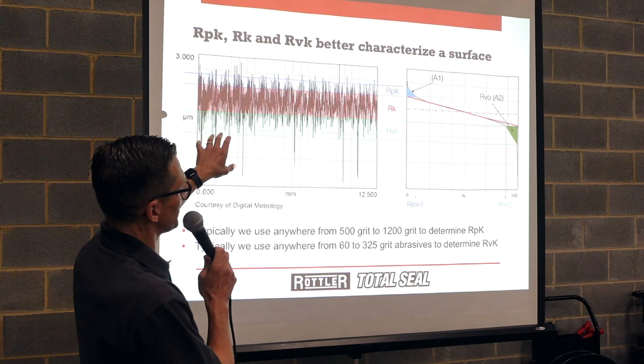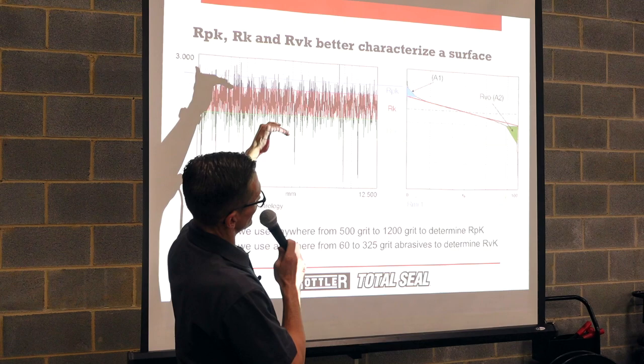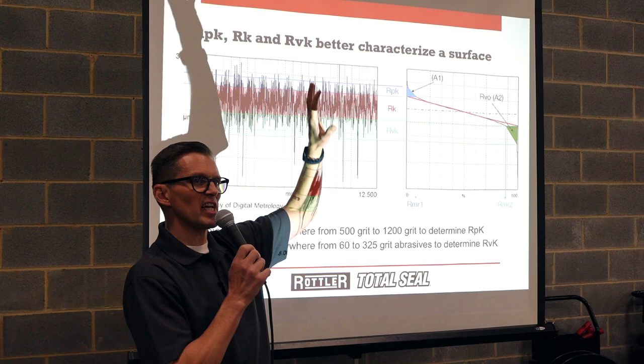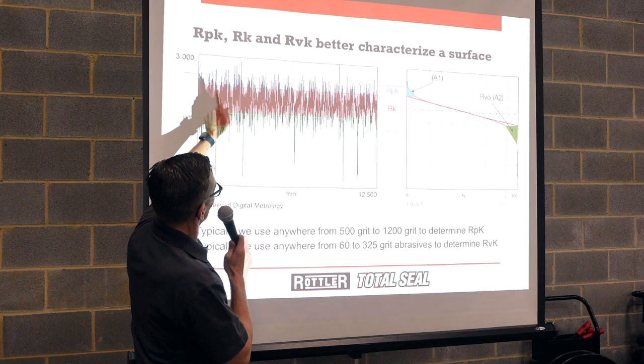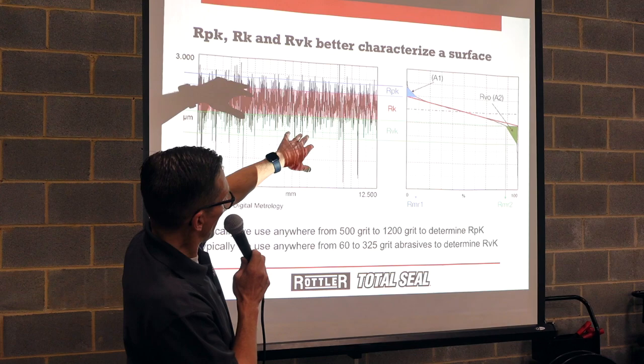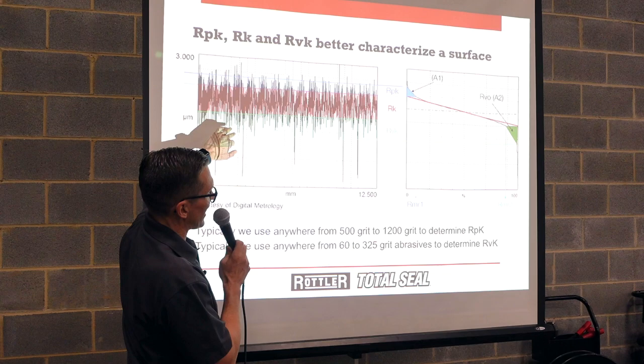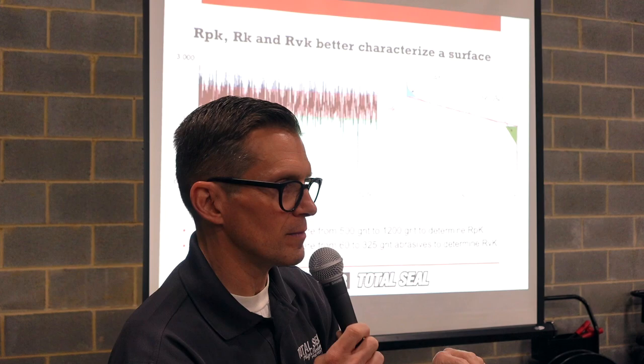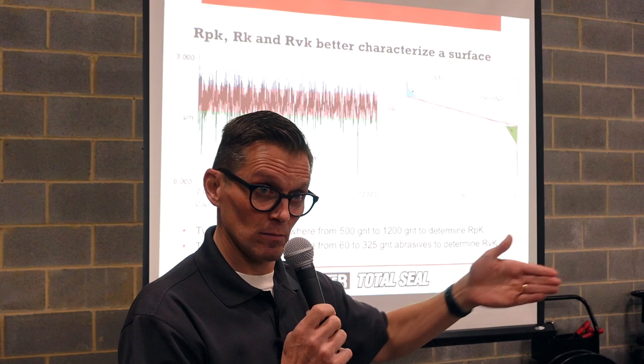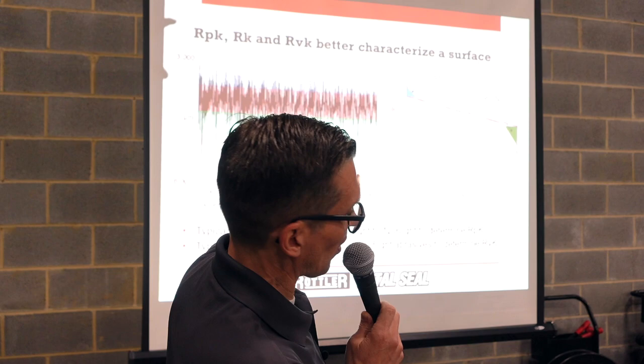So the first thing we want to do is what's called our material ratio curve. And that's going to give you the idea of what that slope is. So that little blue area over here, that's your RPK. That's the stuff that's sticking up. That's what the ring is going to be contacting and hitting. So remember, this is a cylinder wall here. The ring's moving up here, so it's going to start knocking down all those peaks. Then that RK is your core roughness. Then the RVK, that's your valley depth. Those are the reservoirs for the oil. So the RK is what's going to give you the supply, what the ring's interfacing with. The RVK is that valley to make sure that they stay full, that there's always enough there.